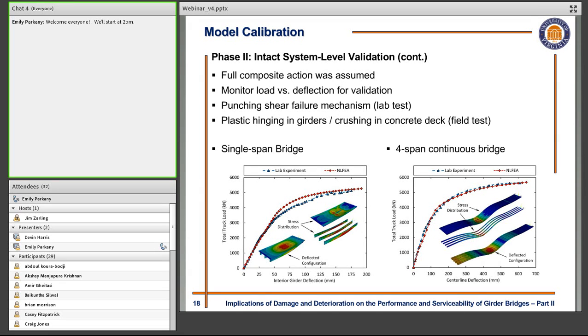As you can see in these figures, the comparison between the numerical results and the experimental data. For the case of the single-span bridge superstructure on the left side, you can see the model was able to capture the elastic behavior, and we had some discrepancy between the results at the initiation of nonlinearity in the steel girders.